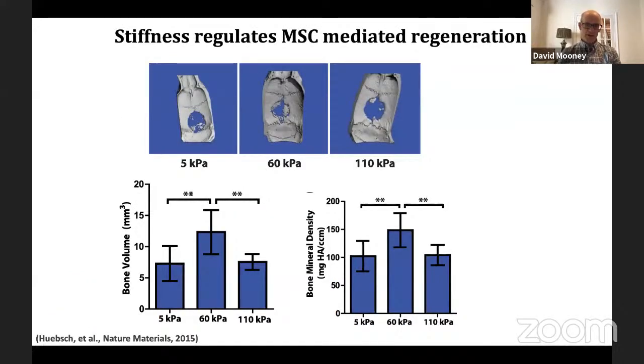And then Nate went and followed that up with a demonstration that this could allow us to regulate the amount of bone regeneration that would occur using these cells in a transplant model. In this case, in a calvarial defect model, he took a small number of cells, transplanted them in gels that were either suboptimal for osteogenesis, either too soft or too stiff, or one that was otherwise chemically identical, but had actually what we consider to be the optimal modulus. And what he found was the amount of bone formation was increased at that optimal modulus that we knew was optimal for osteogenesis in vitro. So the first demonstration in the body that we could regulate the ability of stem cells to mediate regeneration simply by controlling this mechanical property.